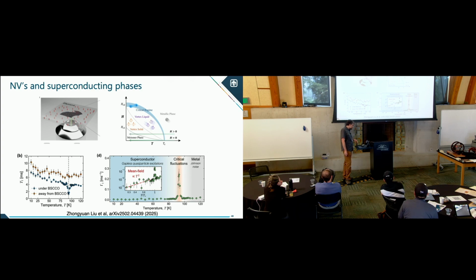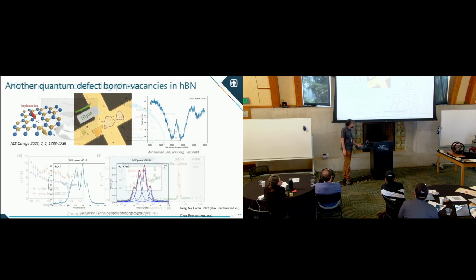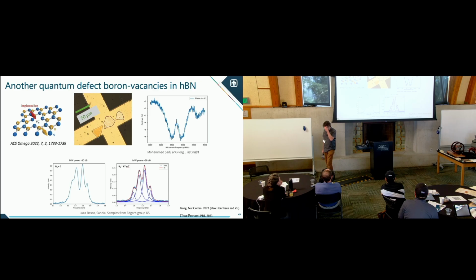Okay, so I want to mention one more defect that we're looking at, which gives an interesting alternative to diamond. I've told you how it's hard to integrate diamond with other materials. You have to really modify the diamond or find the right target. Hexagonal boron nitride, while you can't get the boron and nitrogen to be isotopically completely enriched out, there are a couple tricks you can play. But this boron vacancy is actually quite similar to the NV, as it has a spin 1 state, and you can do optically detected magnetic resonance.